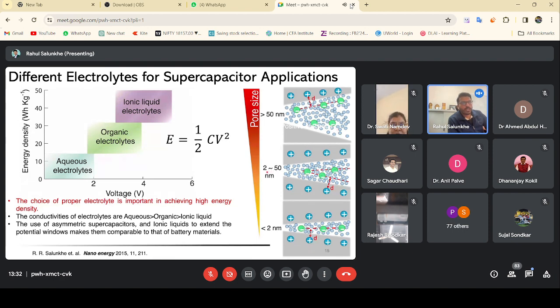Whereas as we go on decreasing the pore size, to 2 to 50 nanometer, the ions get aligned to the surface. Now the interaction becomes quite active within these pores, and when the ion size matches the pore size, the ions get aligned to the surface of the material, and because of that more interaction is possible and more charge can be stored. Because of that, when our pore size is less than 2 nanometer, we can achieve a very good capacitance, as predicted by the theoretical and experimental models.